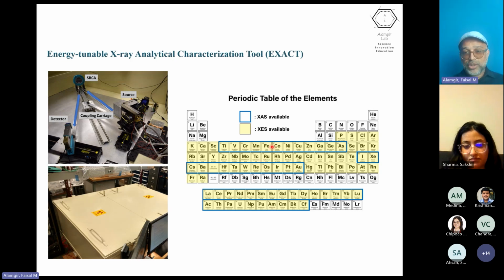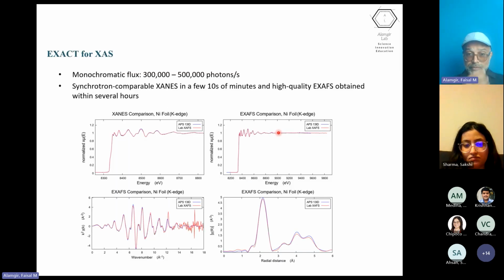But you will notice that we cannot do X-ray absorption of everything, while X-ray emission is possible for a very large swath of elements. The reason we cannot reach all the elements with X-ray absorption has to do with the geometric limits and the particular types of crystals that we currently have. When you do these kinds of experiments, the comparison to beamline, that is synchrotron beamline data, is quite good, albeit with a lot more time needed to get similar quality data.